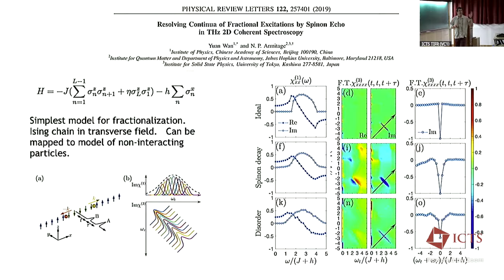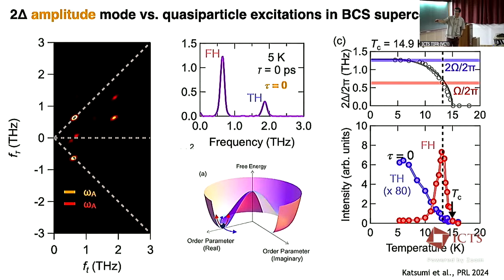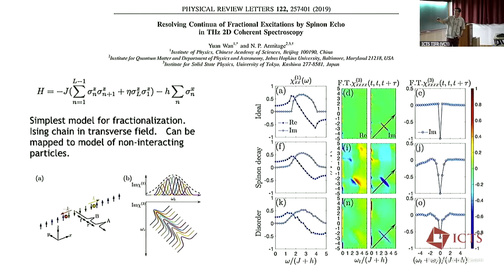And so if I, say, come in with a photon or a neutron, and I flip a spin in the Ising chain, the elementary excitations of the system are these domain walls, which propagate apart from each other, which gives us a broad continuum behavior. Again, each of those oscillators might be very well defined. Each of those resonances might be very well defined, but you can't see it in the linear response because they're all on top of each other. But in the 2D response, you can.